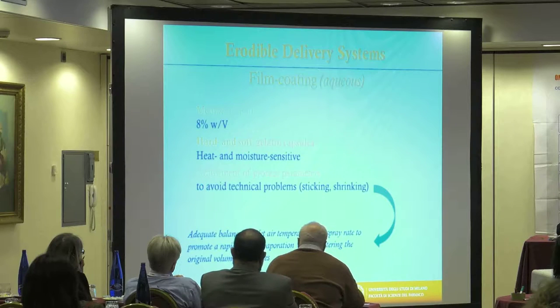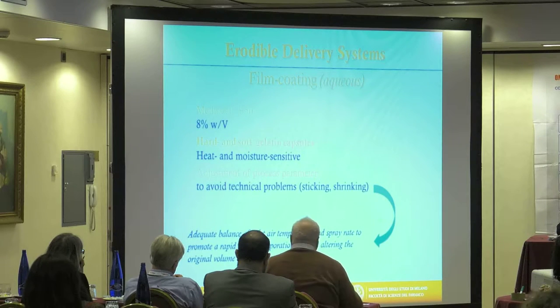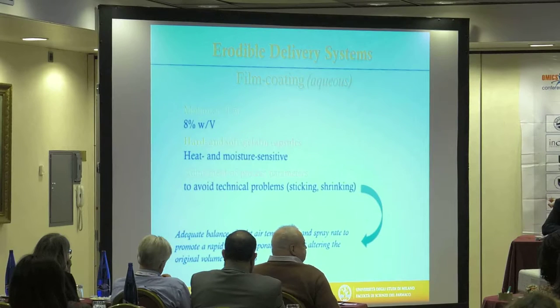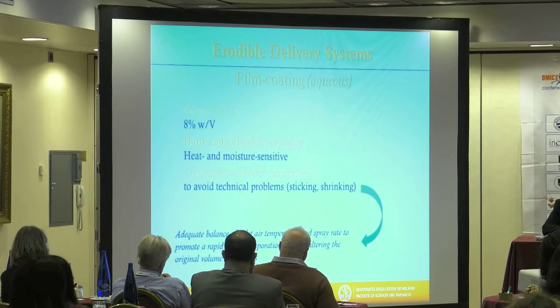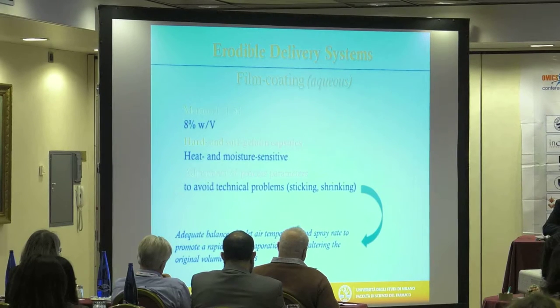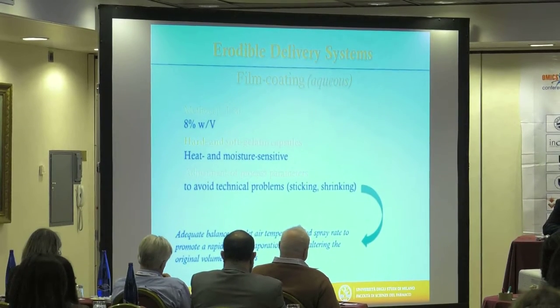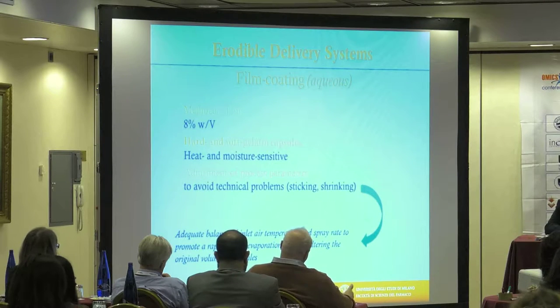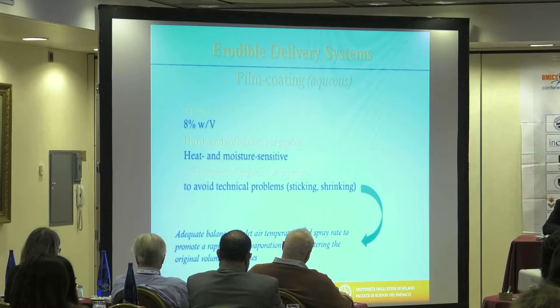This aqueous film coating technology was also applied to hard and soft gelatin capsules when these capsules were used as cores instead of tablets. It was necessary to adjust carefully the process parameters to avoid major technical problems, especially of sticking and shrinking of the heat and moisture sensitive shells, and particularly an adequate balance of inlet air temperature and spraying rate needed to be sought, especially in the initial phases of the process, in order to ensure that the solvent could rapidly evaporate without altering the original volume of the capsules.